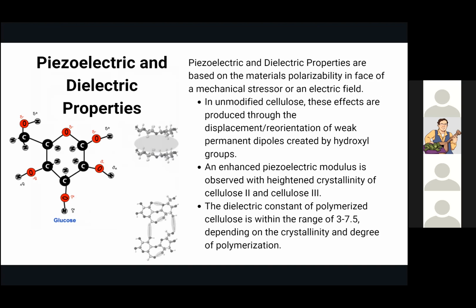So although it is not naturally conductive, cellulose has been shown to be intrinsically piezoelectric and dielectric. As we mentioned with the sensor slide, piezoelectricity is often used as a sensor property for dynamic sensing, and dielectrics can be used in capacitors and capacitive sensing. Both of these properties, in this case, directly relate to the state of hydrogen bonding and aspect ratio of the nanocellulose derivative. They're both based on the material's polarizability in the face of mechanical stressors or an electric field.